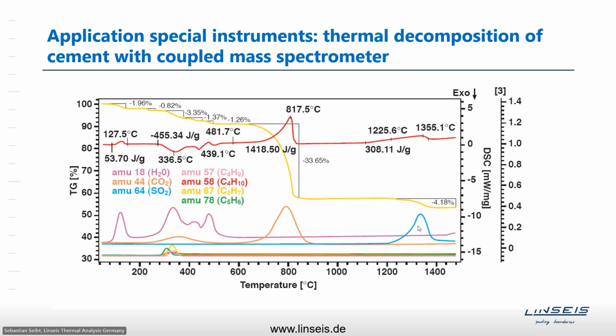And this is how you usually investigate unknown samples that compose or decompose in multiple different steps. So this was a cement sample releasing carbon monoxide, carbon dioxide, some sulfur components, some volatiles, and shows you a quite weird yellow mass change curve, and also multiple effects on this red DSC curve. So this is a real experiment where you see that mass spec can really improve the experiment by telling you what exactly is lost at each segment and at each effect, by identifying the outgassings.